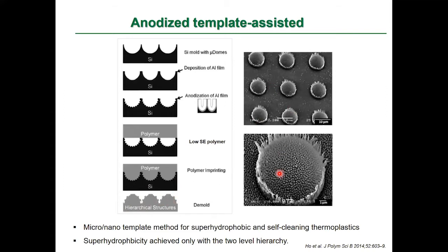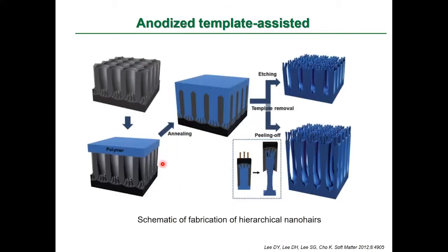So you can see the SEM images. So this is another example. See the anodized aluminum oxide template, the polymer annealed, and it is infiltrated, and its template removed, and it is a very technologically important superhydrophobic surface.